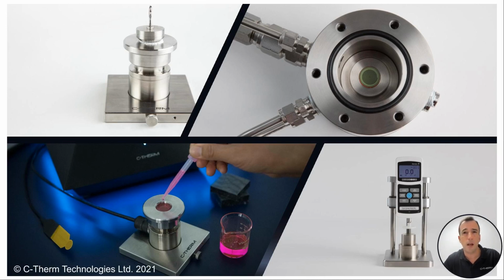Top right is an example of one of our high pressure cells. So in thermal conductivity, really important to test under representative test conditions. Bottom right is something that might be quite useful in testing some types of insulation. You think of batting material, the level of compression of the material is something to report as part of the conditions under which the test was administered. So if you compress a material, you often push out the insulating agent, which is often air. Air has an excellent thermal insulation quality. It has a conductivity around 0.02. But if you densify the sample, that's going to increase the effective thermal conductivity.